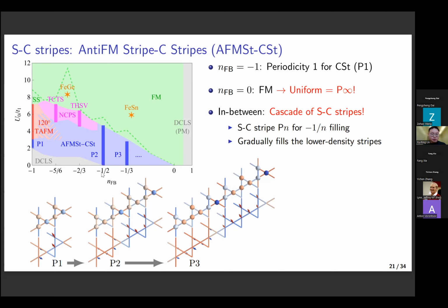For example, if we go to the -1/2 filling of the flatband, we're looking at the half filling between -1 and 0, we're filling half of the lower density stripes. So we're doubling the periodicity. And if we look at the -1/3 filling, we're at the 2/3 filling between -1 and 0, so that we're filling 2 out of the 3 lower density stripes. So this is a very intuitive way of understanding why we have the cascade of the spin and charge stripes.